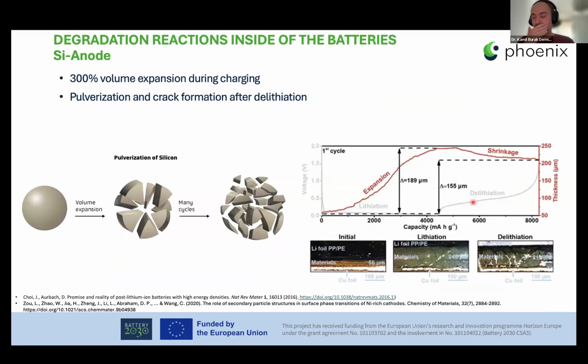When it comes to the degradation reactions inside the batteries, the PHOENIX project uses silicon anodes. Silicon anodes are known for more than 300% volume expansion during charging, which is quite high. As a result, pulverization and crack formation occur after delithiation. After many cycles, you will see very small pieces of silicon, and further SEI will be generated on these newly active surface areas. That will of course have a detrimental effect on the capacity and performance.